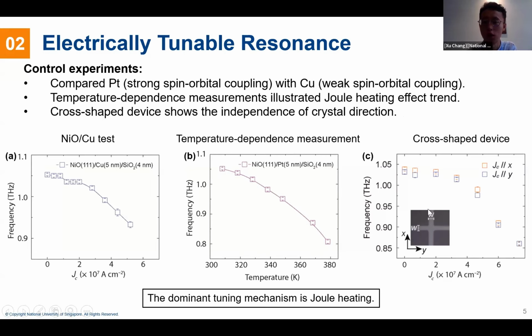Then we also fabricated this cross-shaped device on top of the crystal to double confirm whether this is connected with some phonon-mediated process. But it shows the frequency shift is independent of the crystal direction, which eliminated the possibility of a phonon-mediated mechanism. So we reach our conclusion that the dominant tuning mechanism is Joule heating.